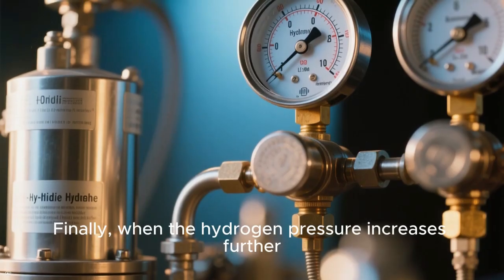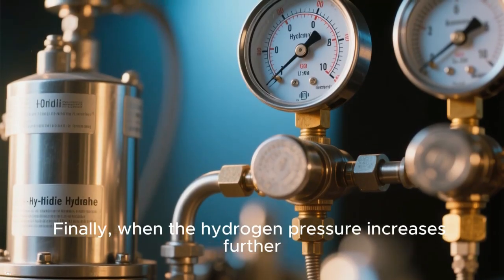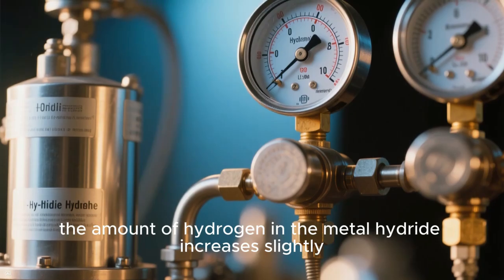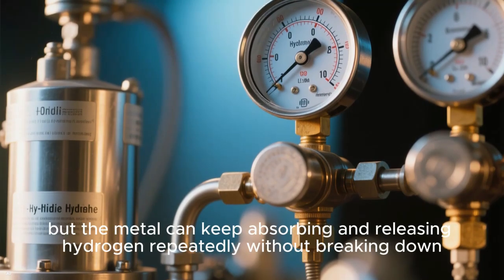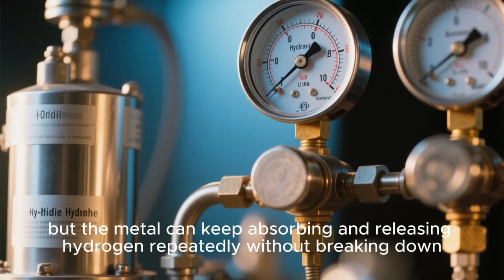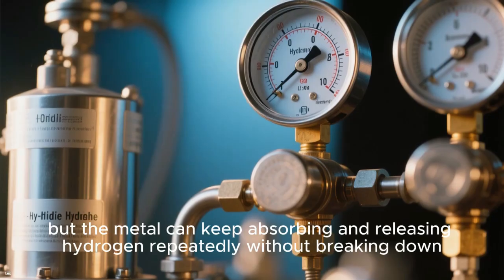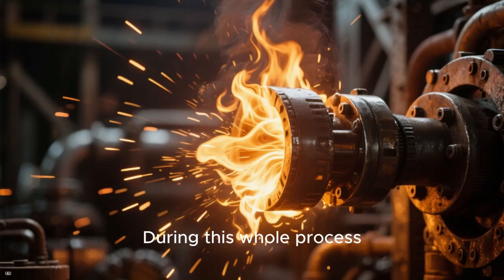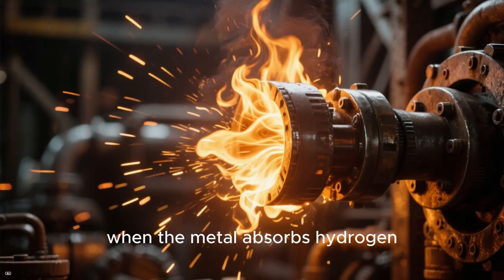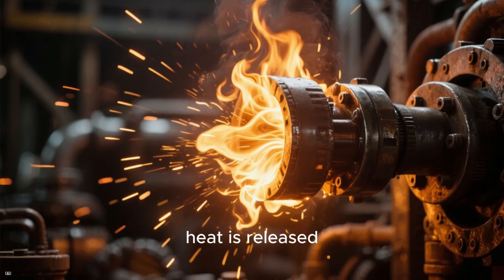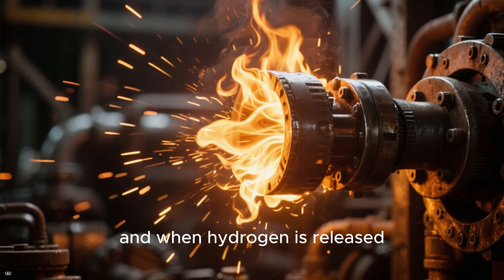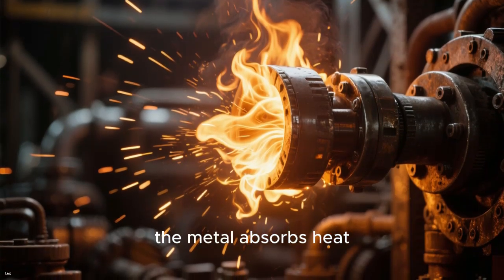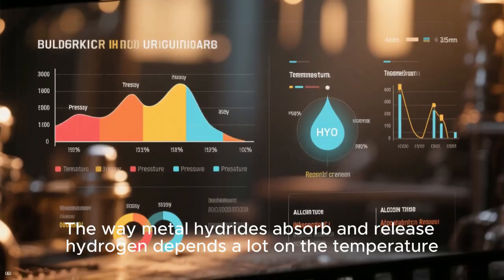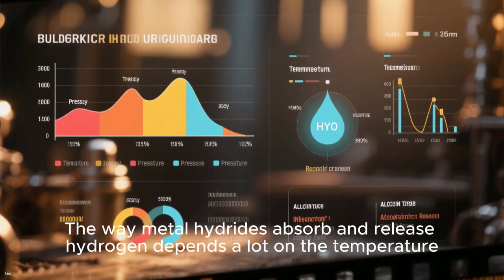Finally, when the hydrogen pressure increases further, the amount of hydrogen in the metal hydride increases slightly, but the metal can keep absorbing and releasing hydrogen repeatedly without breaking down. During this whole process, when the metal absorbs hydrogen, heat is released, and when hydrogen is released, the metal absorbs heat. The way metal hydrides absorb and release hydrogen depends a lot on the temperature, pressure, and the type of